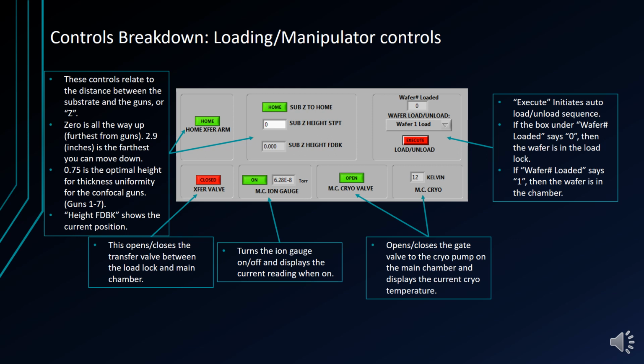With the chuck in the main chamber, we can set our desired substrate height. 0 sets the manipulator all the way up and is furthest away from the guns in position. The largest value you can set here is 2.9, which means the sample is 2.9 inches down from the top. This is not the distance between the guns and the substrate. Be aware that due to the configuration of our system, the best thickness uniformity is achieved at a height setting of 0.75. If you are using the center gun, which faces directly towards the substrate, height can be used to achieve much higher or lower rates.